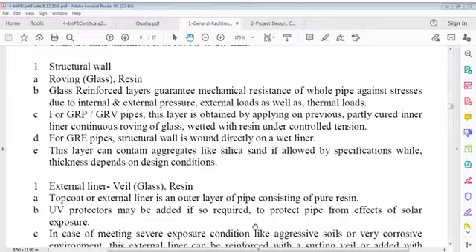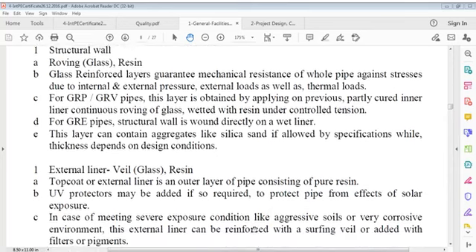Now for GRP / GRV pipes, this layer is obtained by applying on the previous partly cured inner liner continuous roving of glass wetted with resin under controlled tension. For GRE pipes, structural wall is wound directly on a wet liner. This layer can contain aggregates like silica, sand, if allowed by specifications, while thickness depends on design conditions.